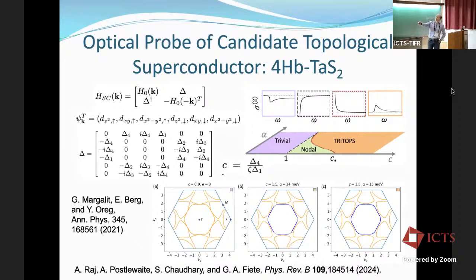And so you can ask, what is the phase of the superconductor? It involves basically two types of pairing on site, which are very important. There's a kind of s-wave pairing, if you will, between same orbitals but different spin. And then there's a pairing between same spin but different orbitals. So it's kind of s-like and p-like. So it's a mixed parity superconductor, and that's very important. There's spin-orbit coupling in the material, which destroys the spin rotational invariance.